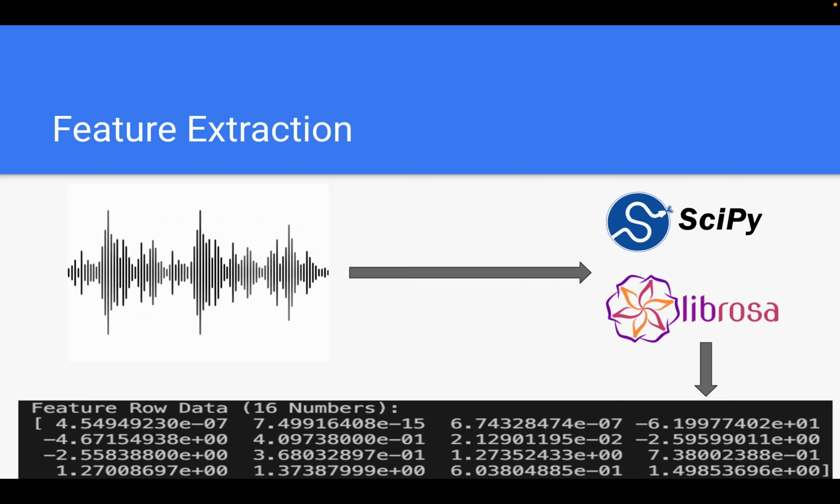And then from that isolated tap, we extracted 2 sets of features. One is the power spectral density. Using Welch's method, we were able to map the sound from the time domain into the frequency domain. And this tells us where exactly the acoustic energy is concentrated. So a healthy cell would ring at a higher frequency, while a debonded cell would vibrate loosely. That's something we already have previous knowledge of, which is what we're taking into this machine learning script. So we extracted the mean, variance, and maximum power from the curve.